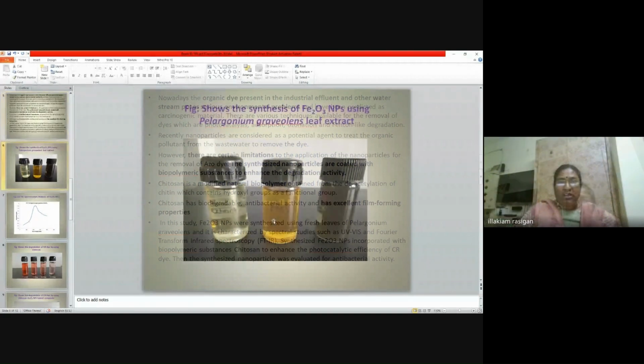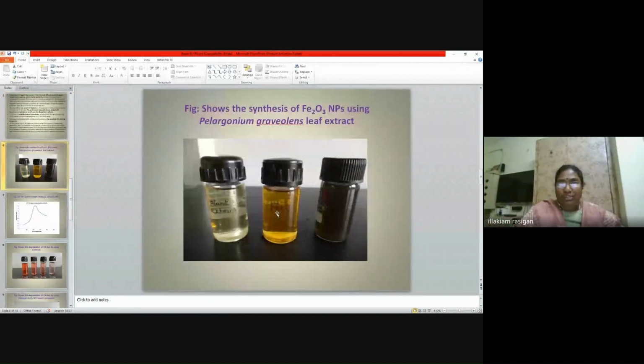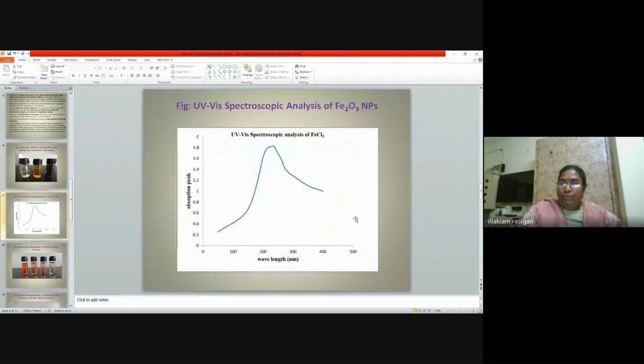I have checked the synthesis of nanoparticles using this leaf extract, Pelargonium graveolens. In this, I have prepared ferric chloride as a standard. I have added an equal amount of plant extract and ferric chloride, and incubated at room temperature. This yellow color is converted into a black color. I have checked whether it is a nanoparticle or not in UV-vis spectroscopy. The presence of this absorption peak proves that the nanoparticle is synthesized using this leaf extract.